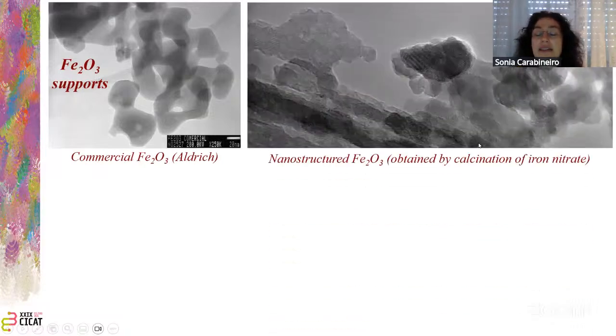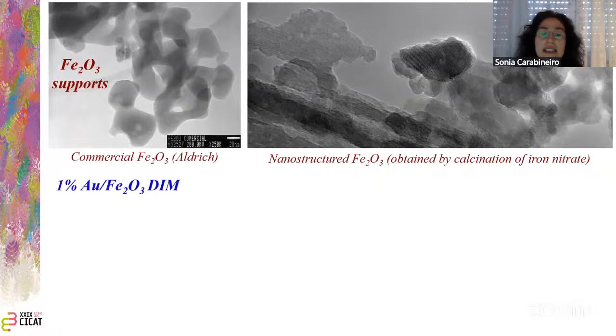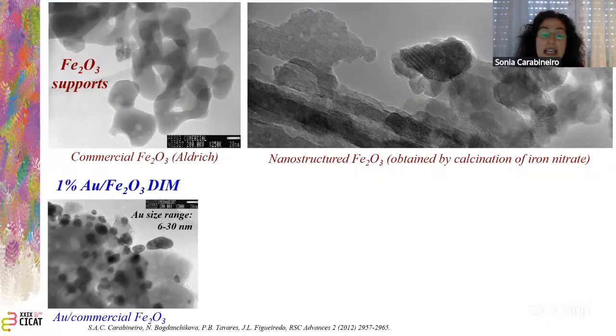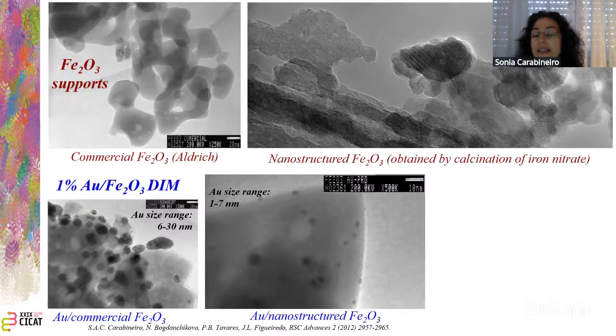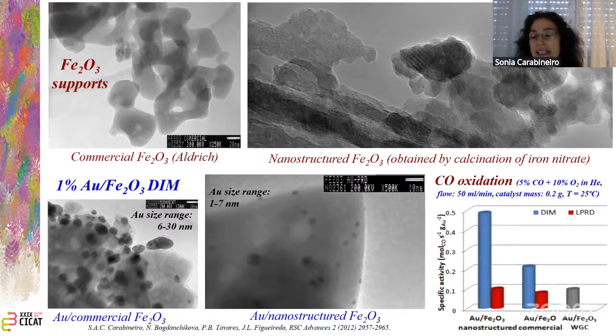We have here nanostructured iron oxide obtained by calcination. So we obtained much larger gold nanoparticle sizes on the commercial sample than on the nanostructured sample, and this was reflected in the catalytic activity. So you see here that gold on nanostructured oxide was much better. And this is compared with the World Gold Council reference catalyst, so these ones were better.